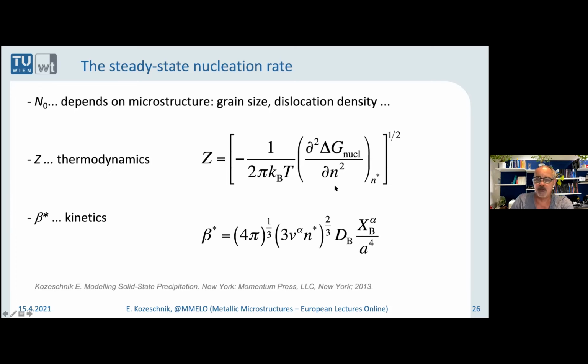So if you go into more detail of nucleation theory, you will find that the curvature of the barrier is the most important quantity for the prediction of nucleation. So it's a thermodynamic quantity, right? It contains the nucleation energy. And then we have the beta star, which is related to diffusion coefficients. That's more or less a transport coefficient. How fast can atoms or molecules be transported within the volume?